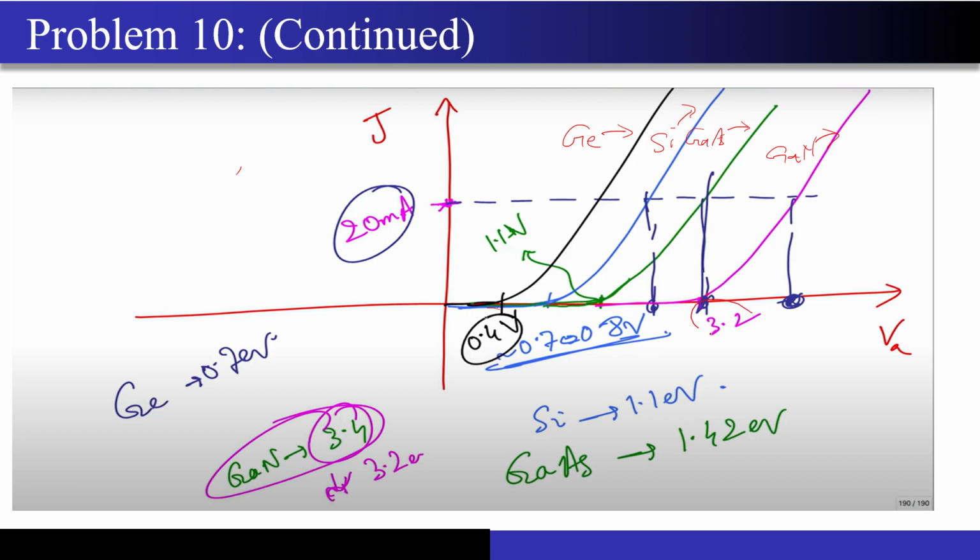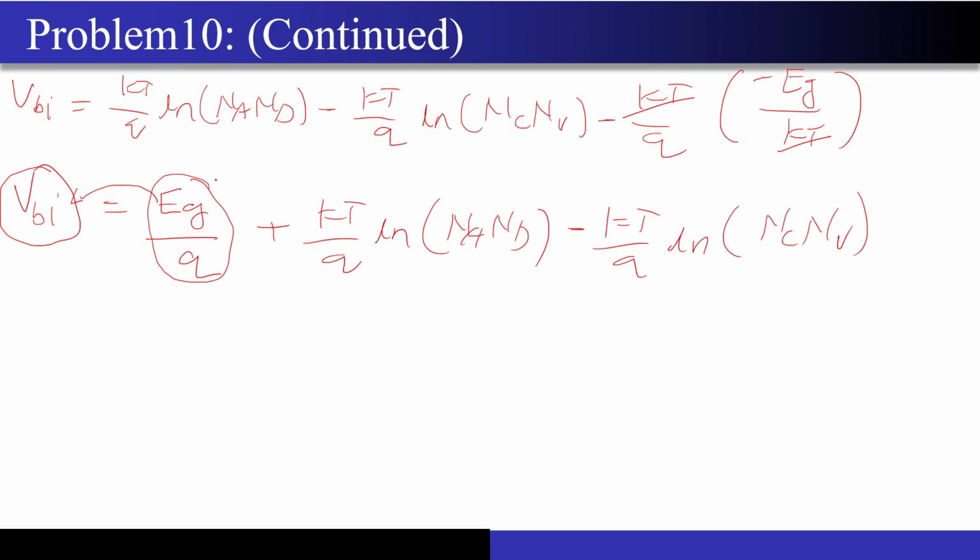For gallium nitride, you have a higher built-in potential compared to gallium arsenide, which is higher compared to silicon, and the built-in potential of silicon is higher compared to germanium, right? And this was just a mathematical proof of the same. Your VBI is exactly proportional to Eg that you got over here. I hope the person who asked this question in the last session, how the Eg relates with the VBI, now gets a clear answer, as I had not given the direct answer earlier.